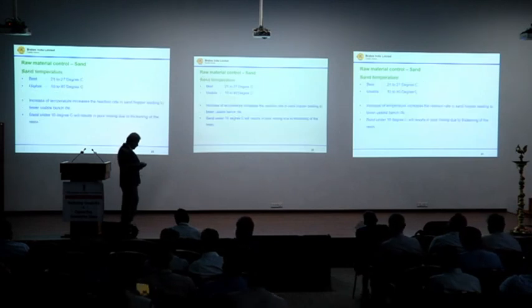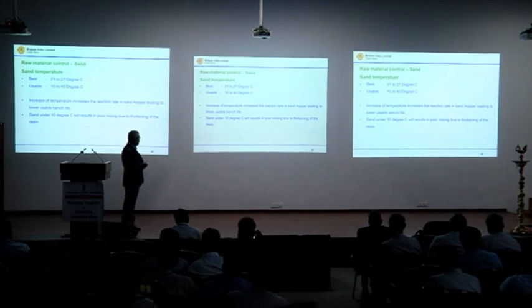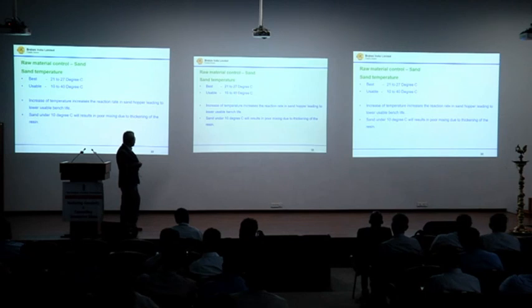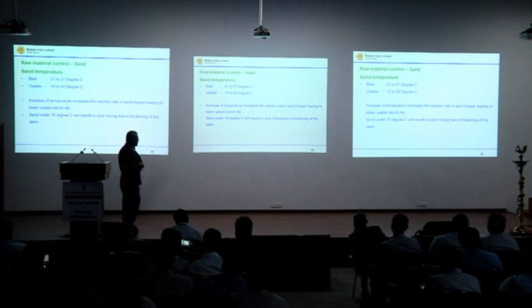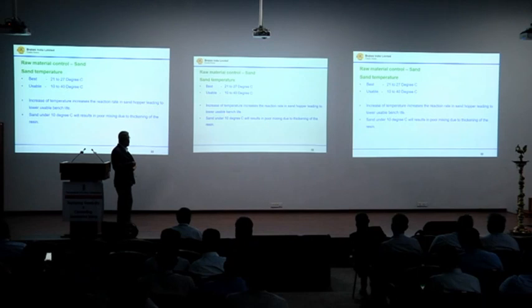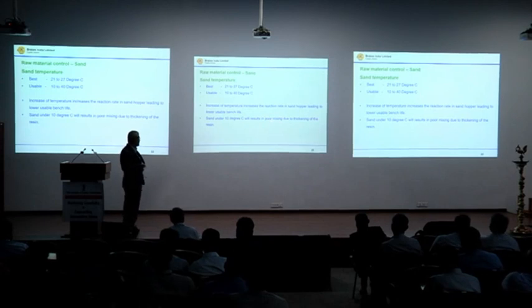Sand temperature: best is 21 to 27 degrees centigrade, usable is 10 to 40 degrees centigrade. Increased temperature increases the reaction rate in the sand hopper, leading to lower bench life. Sand under 10 degrees centigrade will result in poor mixing due to thickening of the resin, so mixing will be a problem at lower temperatures.